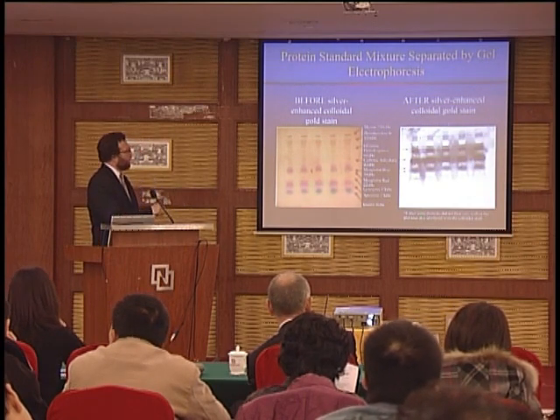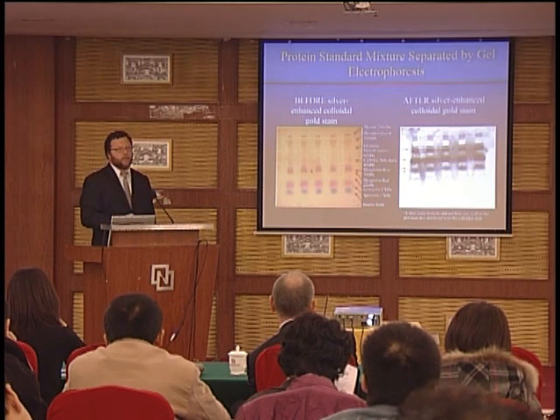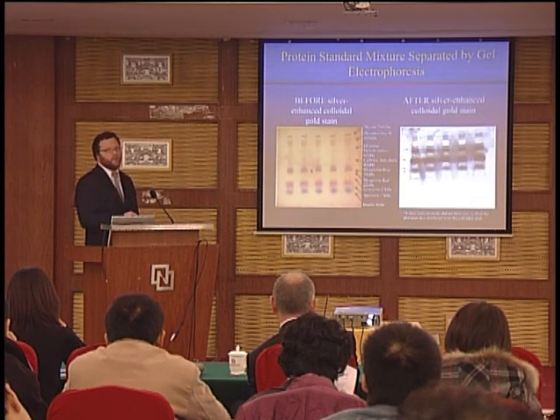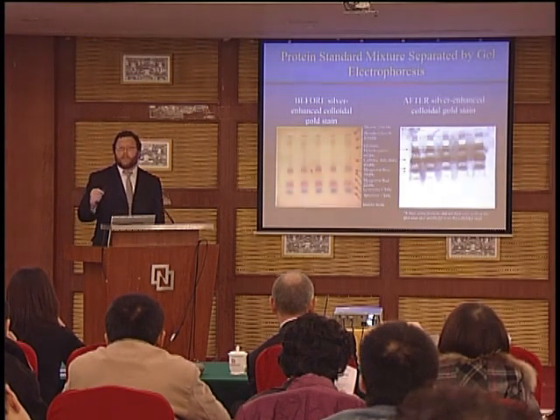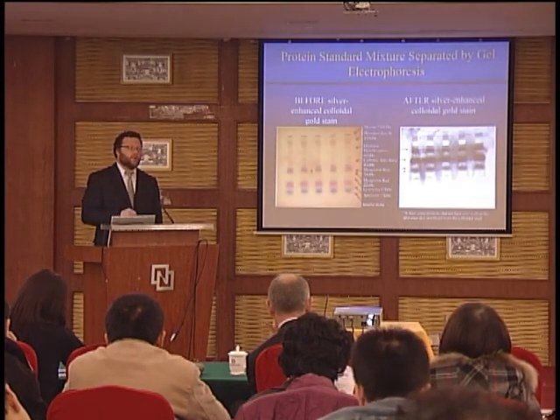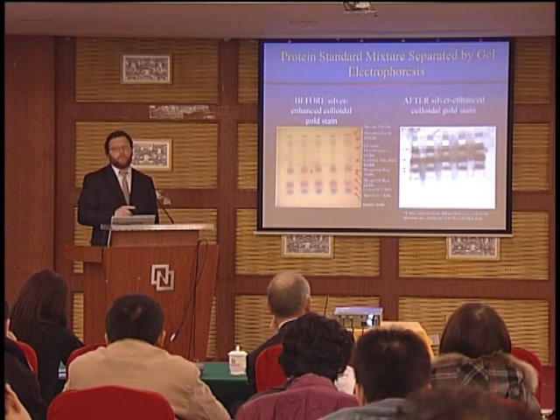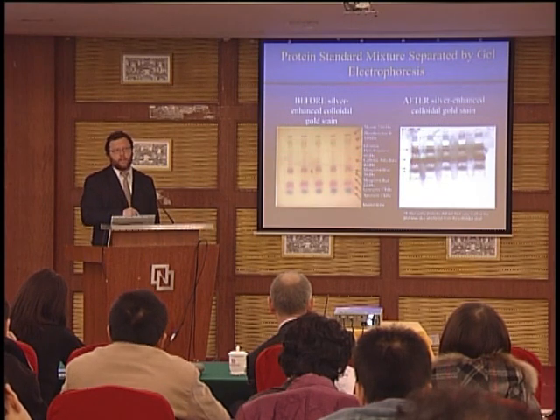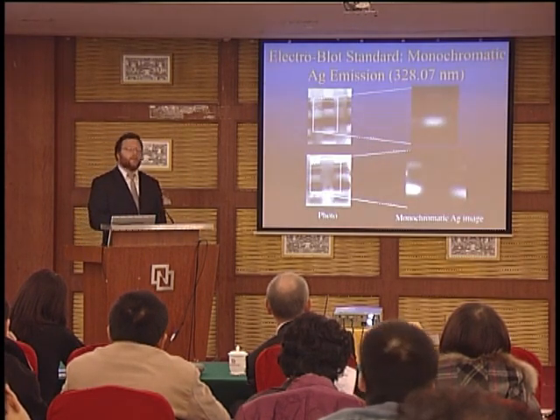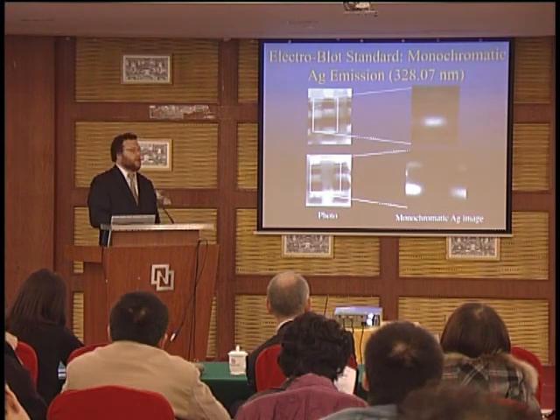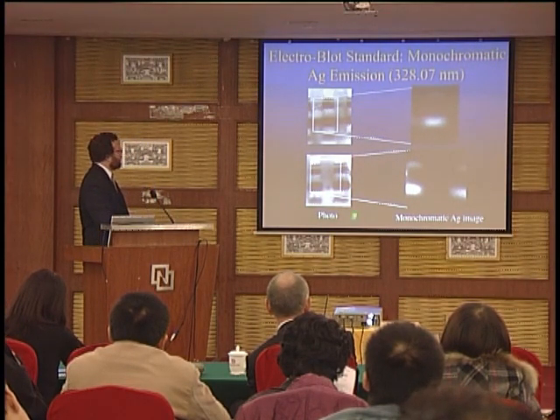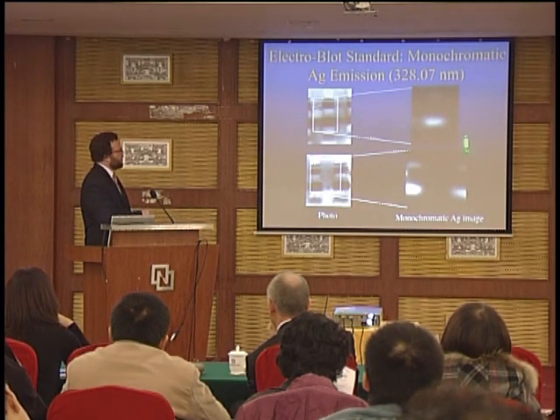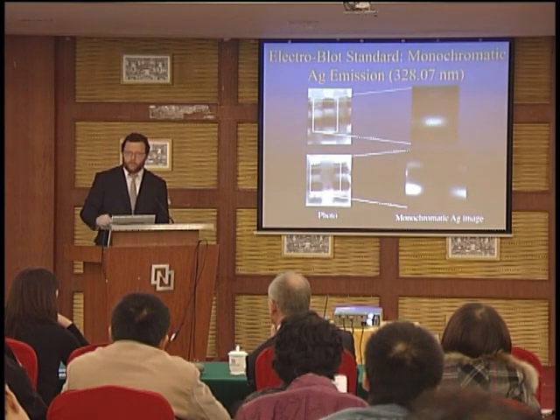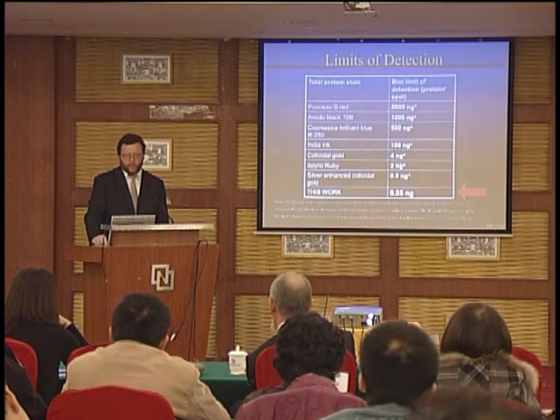First, this is a photograph of exactly what the blot material looks like. The thing that you note is that there's a different sensitivity for the amount of silver that's actually attached to each one of these proteins by non-covalent bonds. And that's kind of a problem with quantitating by this methodology. But you see, if you place it into this type of system, you can get proportional response. This happens to be a photo of what the section will be excised, and then if we do the glow discharge atomic emission spectroscopy, you can see that you see silver emission at the correct wavelength.